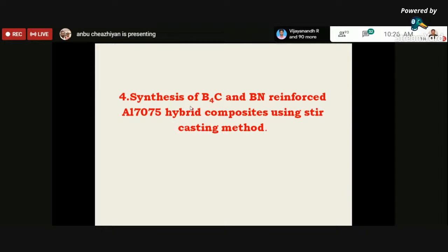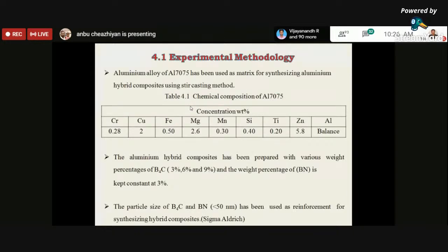So this is the experimental methodology that we have followed. Aluminum alloy Al7075 is used as the matrix material, and this is its chemical composition. Here we have used boron carbide and boron nitride as reinforcement. We varied the boron carbide percentage at 3%, 6%, and 9%, and kept the boron nitride constant at 3%. The particle size of boron carbide and boron nitride is less than 50 nanometers, which is commercially available from Sigma Aldrich.